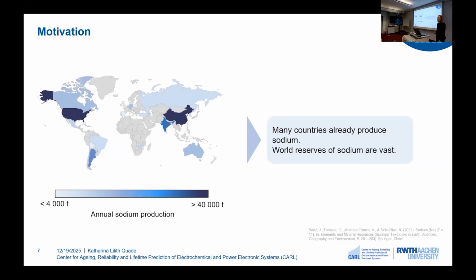So, to summarize, if we aim to reduce the global dependence of the lithium-ion battery supply chain, we must find alternatives to lithium. And sodium might be an attractive candidate from a sustainability, cost, and also supply chain perspective. However, we've seen that sodium has less favorable electrochemical properties, and this limits its replacement to applications where such performance trade-offs are acceptable. And this in particular includes applications where we do not need high gravimetric energy density. I will now present such a use case, on which all my further analyses are based.